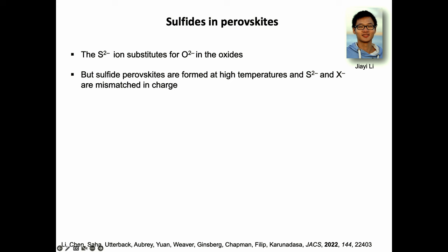Anytime you have lead and sulfide in solution, guess what you make? You make lead sulfide. It's a thermodynamic sink. It's very hard to fight this. So we cannot have lead and sulfide in solution if we don't want to make lead sulfide. So Jiayi decided to address all of these problems by looking not at sulfides, but organosulfides.